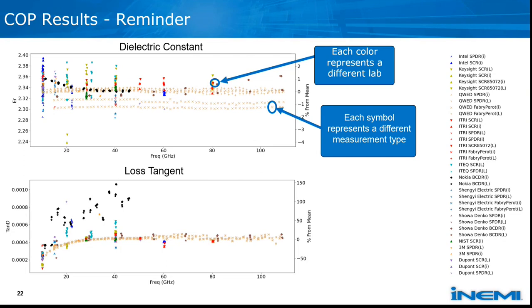So this is essentially an overlap of all of the COP measurements that were done, and from this chart we break it out by the lab and by the equipment set that was used in the individual lab. I think the key takeaway from this is that, given an almost perfect sample of COP material, you can't really expect to get a result that is better than, say, plus or minus 2% in terms of dielectric constant. The spread in loss tangent you can see from the plot below. This really is as good as we can do as an industry.